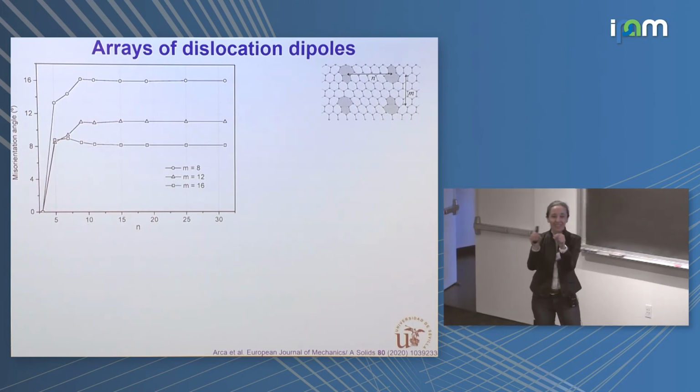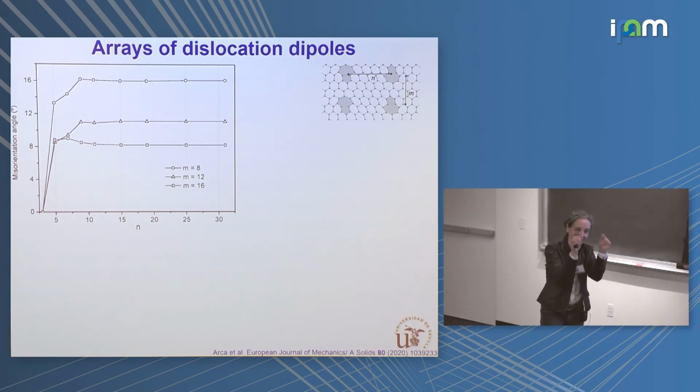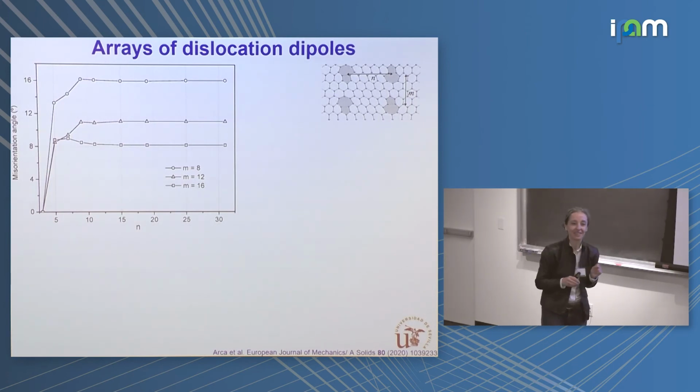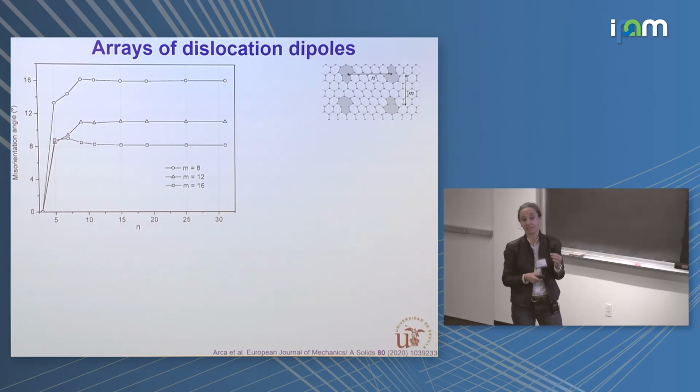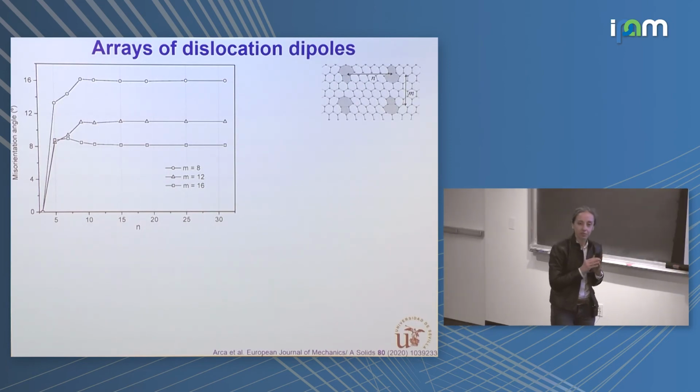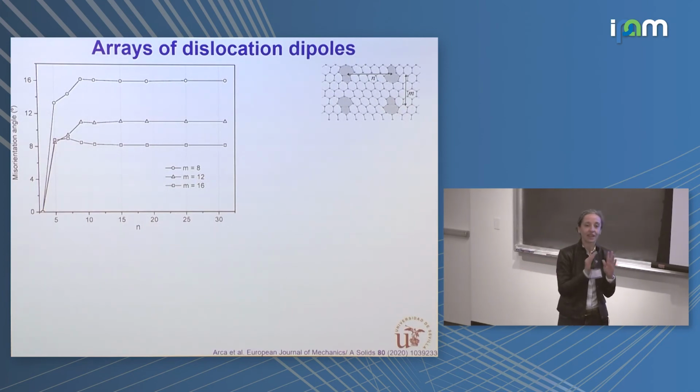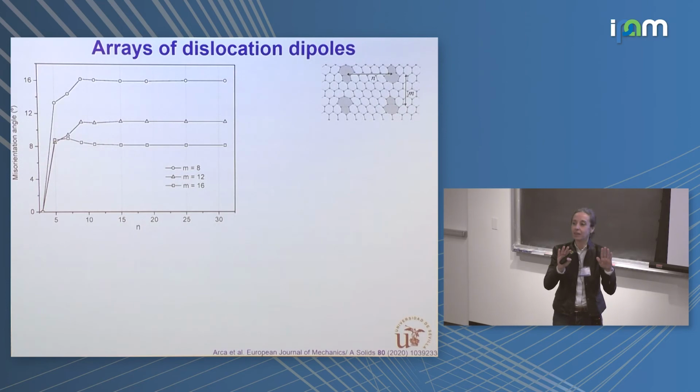For that, you have to check that the equations that define twinning are the ones that you can see here. The values of the misorientation angles are exactly the same. This is not grain boundaries. When I defined grain boundaries, I set up grain A and grain B, I rotated one with respect to the other one, and I relaxed the configuration. And the 5-7 rings appeared with a different periodicity along the grain boundaries. This is a completely different thing.